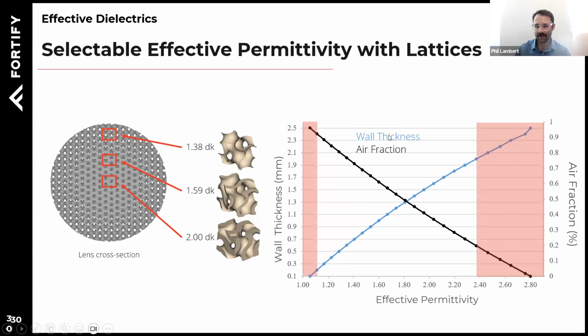We look at the wall thickness of our gyroid in this blue line here. As our wall thickness goes up, our effective permittivity goes up, and that's because the wall thickness controls our air fraction. So as the wall thickness goes up, we can also see that our air fraction line, this black line, goes down, and our effective permittivity goes up. Therefore, to summarize, the more material you have in your unit cell, the higher your effective permittivity is going to be. But we have limits here.